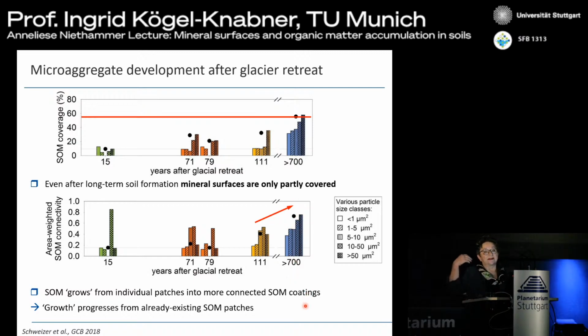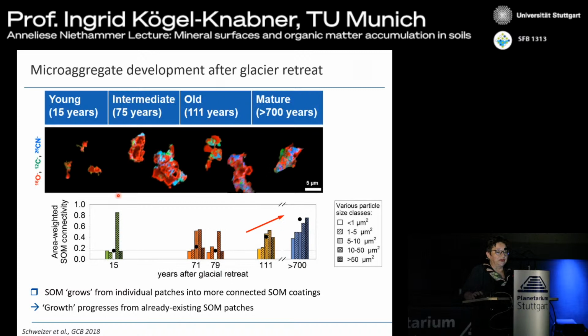And this confirms what we've seen in our lab experiment, that the growth progresses from already existing organic matter patches. But if time is longer, they enlarge and produce larger associated particles that have a lot of organic matter connected to each other on these very fine particles. Small, very small microaggregates, let's say.